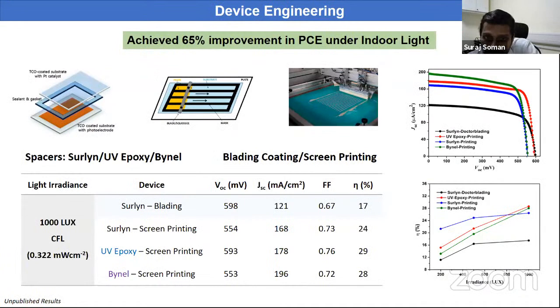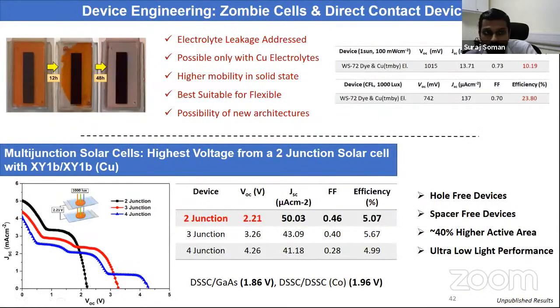Another part is varying the engineering side, like varying the kind of deposition. We normally use doctor blading, screen printing, and gravure coating. We checked a couple of different techniques, and we have figured out that with bilayer sealing and screen printing, we can custom tune the efficiency with the standard materials to realize somewhere around 18%, 28%.